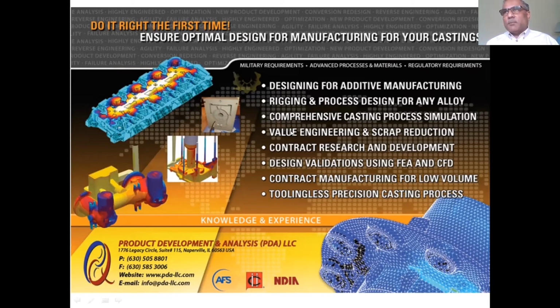So you have to do a lot of post-processing, and there are a lot of issues with warpage and overall cost, because the envelope size is still limited to maybe 2, 3, 4, 5 cubic feet. Whereas our approach, the technology of additive for metal casting, is like Lego style: we can make a huge mold, 20 feet long. You can make it in 6-foot segments and glue it together and pour the metal. And once you pour the metal, the whole melting, pouring, solidification, cooling, removal of risers and gates, everything is the same as the conventional. So I know it's a long answer, but